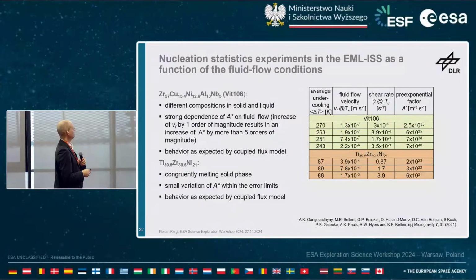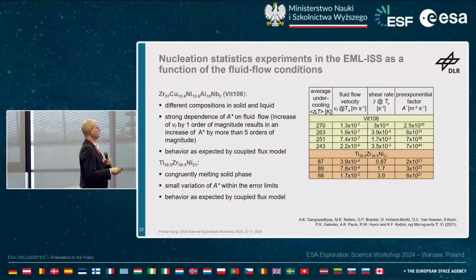So this has been done for two systems. So the Vitralloy 106, shown here, and the titanium, zirconium, nickel. So what do we see here on the right-hand side? So this is the experimental analysis. The analysis of the experiments using the model, basically. And so what we get is, let's say, an average undercooling from fitting this nucleation statistics. And this is on the one hand for Vitralloy 106 and for the titanium, zirconium, nickel down here.